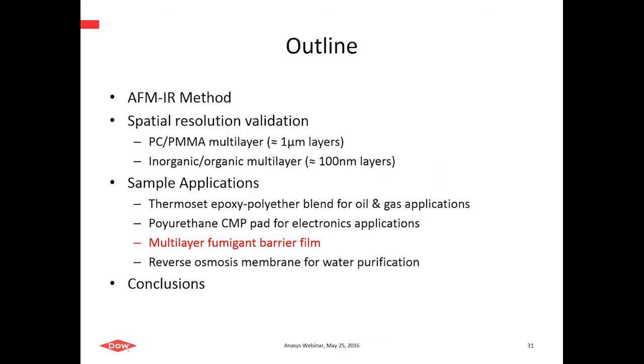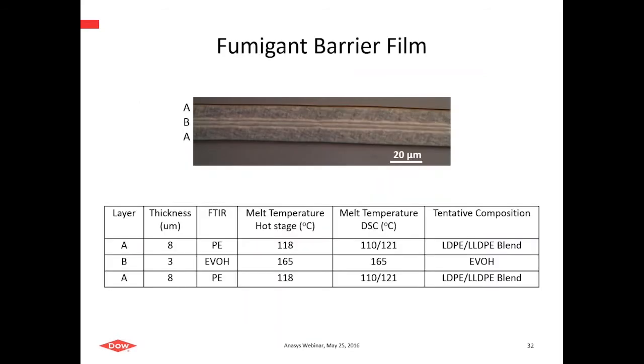Okay, so let's move on to another application. This is a multilayer film next, and this is for agricultural applications. It's a fumigant barrier film. It turns out that generally something like FTIR or Raman is sufficient to characterize a lot of these packaging multilayer systems, especially when the layers are very thick, although we've already talked about diffraction limited optics in those cases. And in many cases, when these films are made, the layers, especially barrier layers or glue or tie layers, can be very thin, less than a couple of microns thick. And that makes conventional methodologies nearly impossible to use. And so this is where something like AFM-IR can really shine.